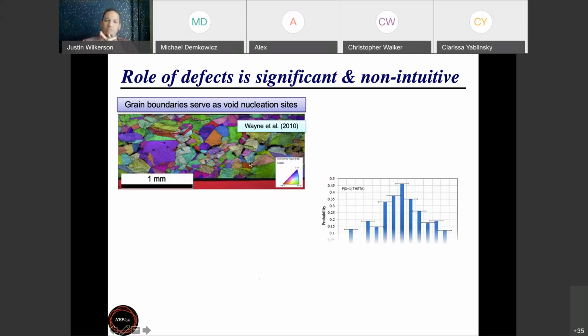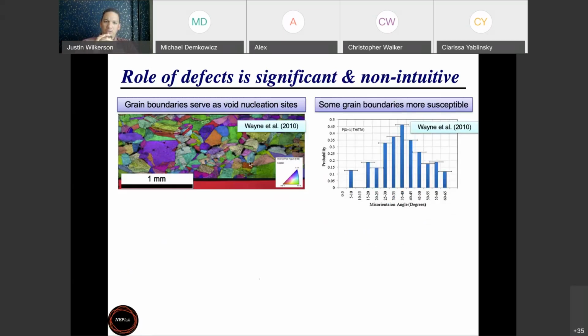boundaries. If you do a more thorough analysis of what's going on as far as damage along certain types of grain boundaries, what you find is that some grain boundaries are actually more susceptible to spall failure than other grain boundaries. So here we have the likelihood that any randomly selected grain boundary will have damage on it as a function of the misorientation angle of that grain boundary. And what you see is that for low angle grain boundaries, you tend to not have much damage. For intermediate grain boundary angles, you have the most likelihood of forming, so those are the most susceptible to spall failure. And then the high angle grain boundaries are the least susceptible to failure. This is biased by the fact that a lot of these high angle grain boundaries are actually sigma 3 twin boundaries in this particular experiment.